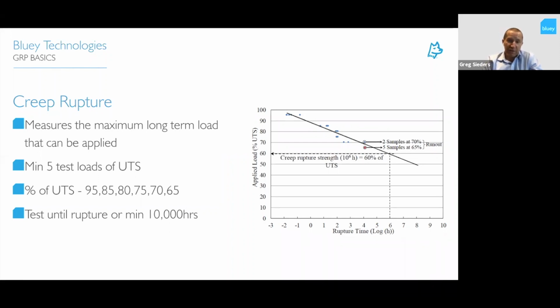And you've got to hold that until it ruptures, or for a minimum of 10,000 hours. So 10,000 hours is equivalent to about 13 months of testing. So it's a lot of testing that needs to happen. And we've done this about 4 times on our bars. Every couple of years, we get bars sent over to the University of Sherbrooke in Canada to get them to retest it to make sure that we're getting the same quality out of the fibres, out of the resins, and out of the manufacturing process.